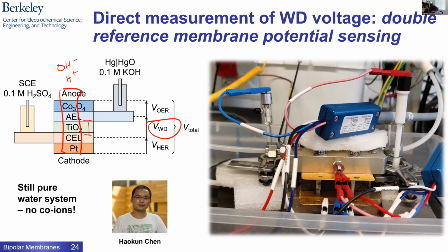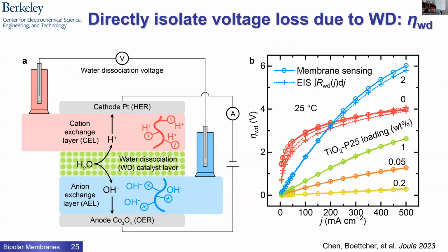I want to emphasize this particular technique, which is very simple and very fast. It allows us to sense the electric potential with a reference electrode, even though this reference electrode is outside of the cell. The electric potential is relatively constant through this strip of membrane that brings the electrochemical cell outside of the actual current carrying part of the cell. We do that for both sides, for the acidic side and the basic side, and then we put two reference electrodes in, and this allows us to directly measure the actual voltage very fast across this junction. So we did a lot of calibration and making sure this all makes sense. I could tell you how it matches the impedance spectroscopy and those resistances I was telling you about. It all works in quantitatively correct ways, so we can use this to look at some important parameters.